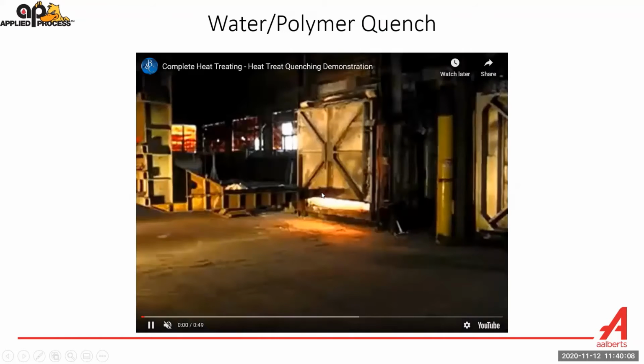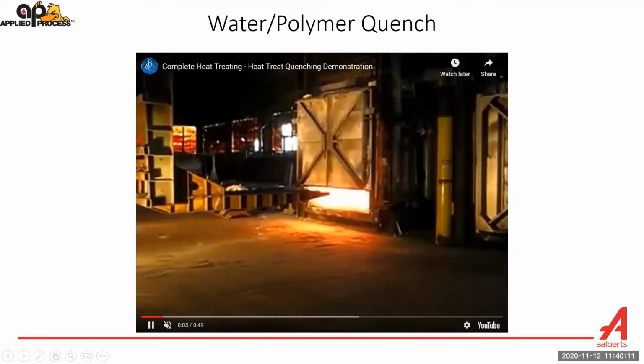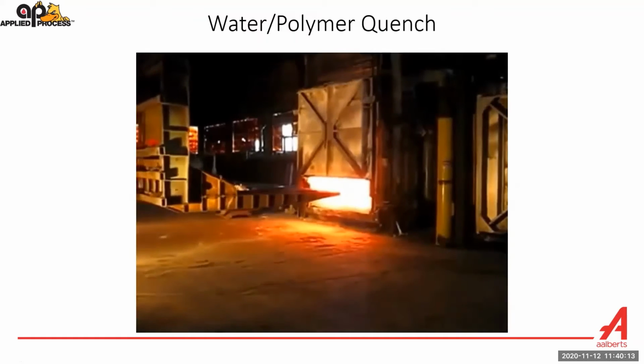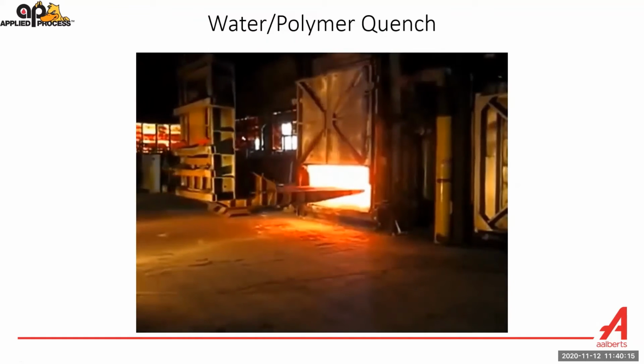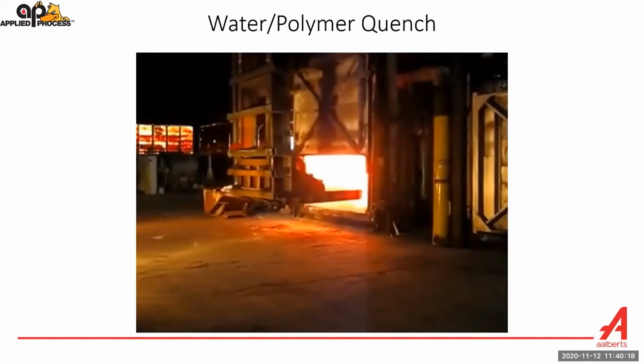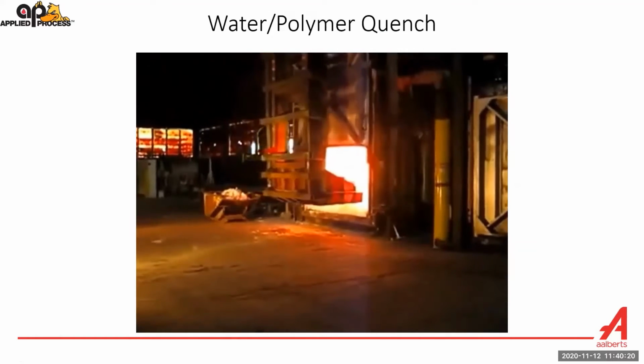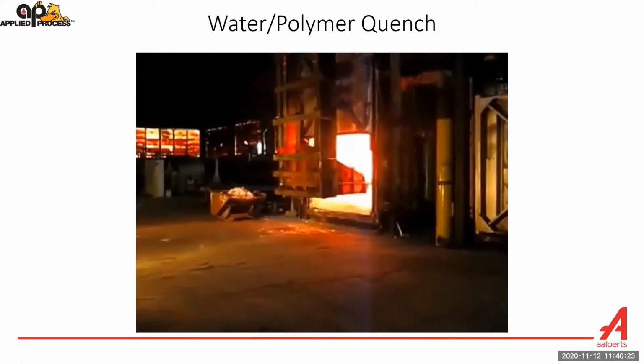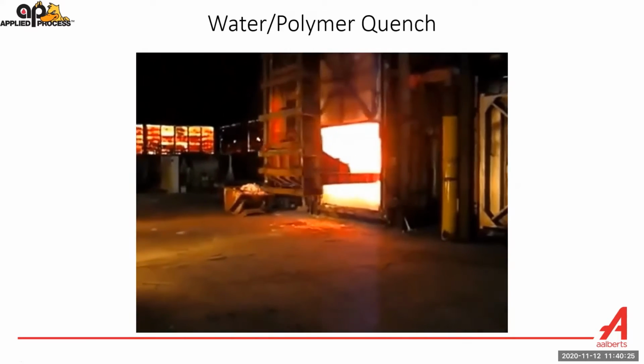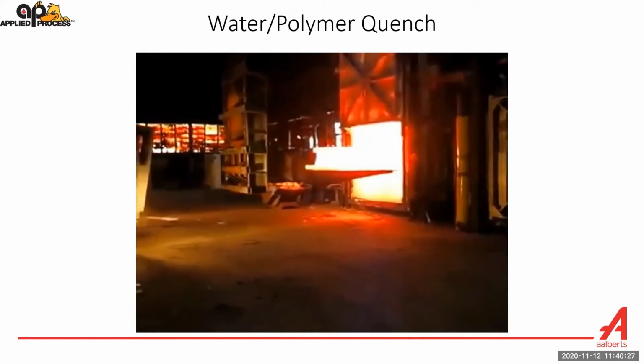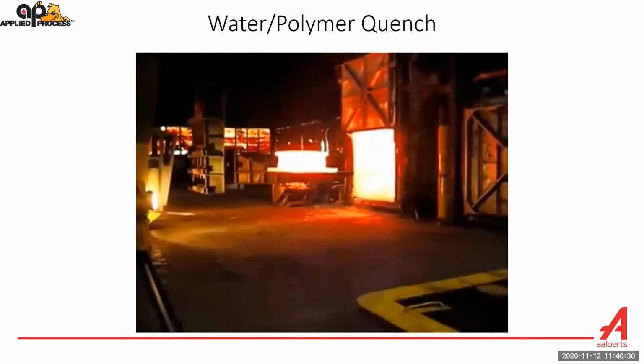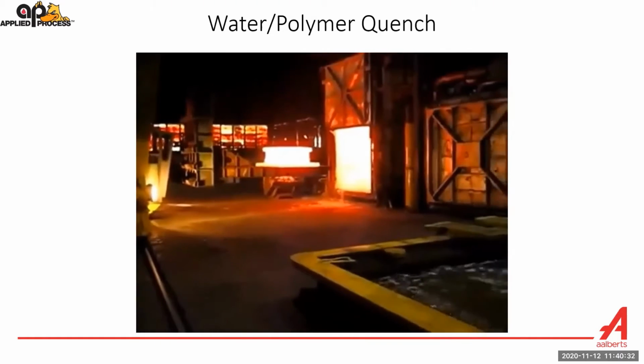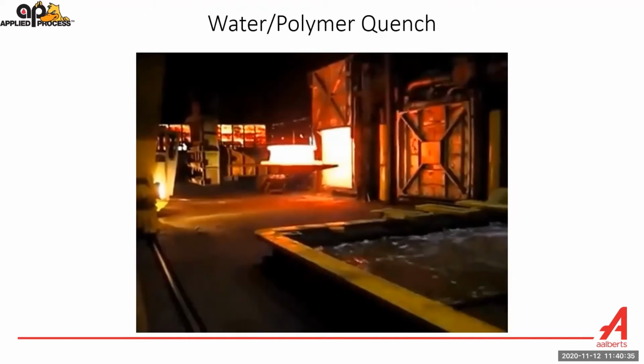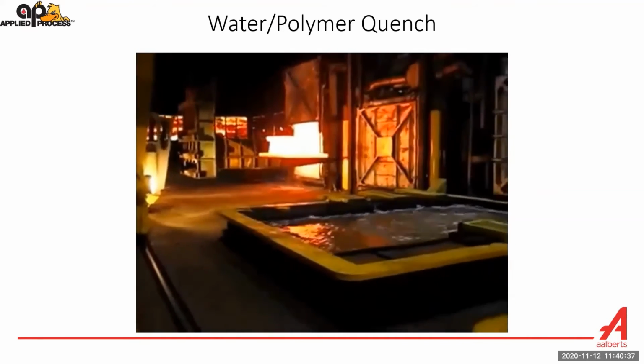Another common heat treatment method would be water or polymer quench. And again, the parts are being taken out of an open fire furnace. These parts are stainless steel rings that are being solution annealed. They're about 2100 degrees Fahrenheit when they come out of the furnace in this case. And then they're transferred to a quench tank. This is a polymer quench tank. And you'll see that the part rapidly cools off.